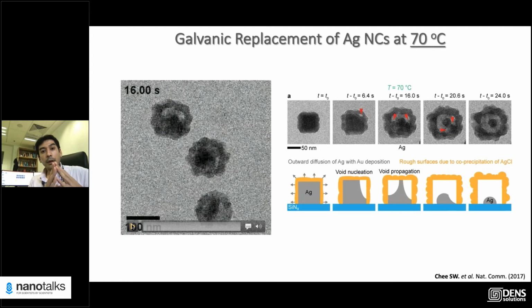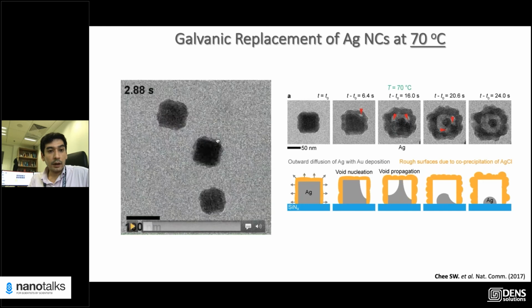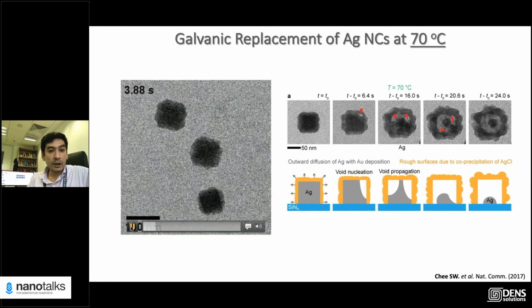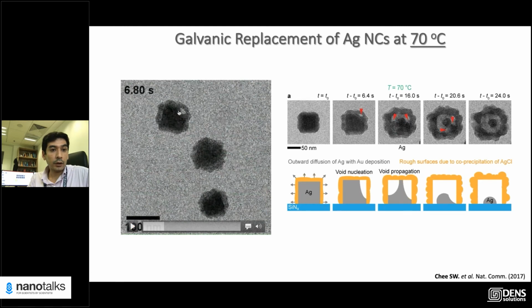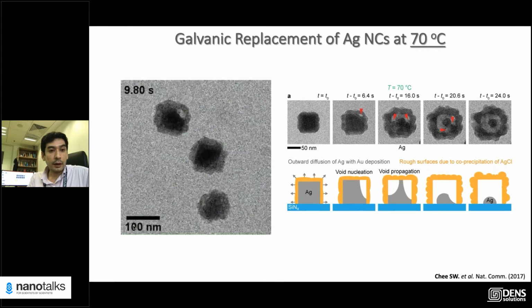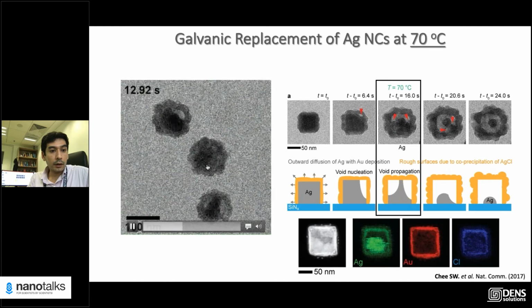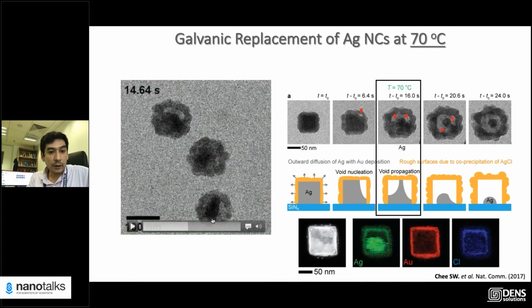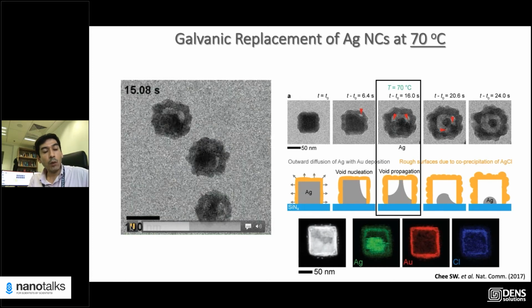If the etching goes through the pits, then at any point you should always etch the core. If you have a hole, then something should diffuse in and eat away the core. So when we look at this movie, you see the deposition on the surface is happening. It's not clear if there are pits or not, but since the reaction is slow enough, we can see that hollowing happens right at the corner of the metals, and then it's slowly etching away. Same here, same here. So it's not pointed out.